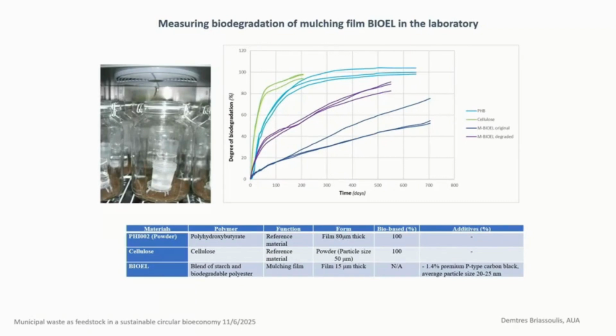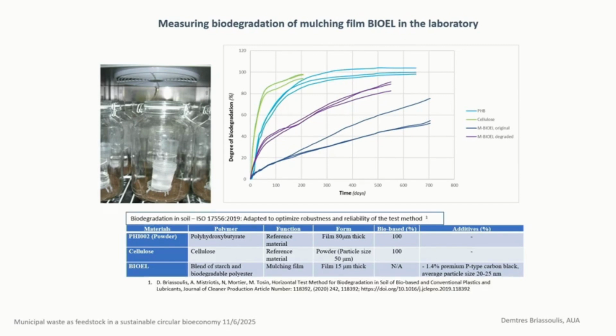Biodegradation is measured in the laboratory using the provisions of international standard test methods like ISO 17556. You see here with the blue and green line the positive reference materials, PHB and cellulose, and the purple curves show the BIOEL film we saw before for disintegration in the field, following artificial aging in the laboratory.